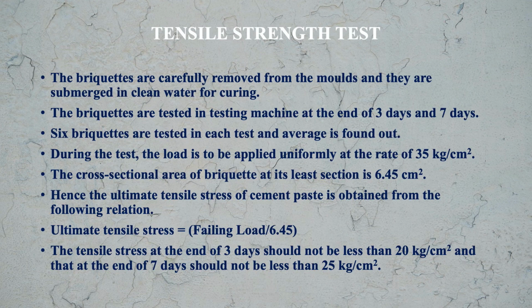Now the briquettes are carefully removed from the molds and they are submerged in clean water for curing. The briquettes are tested in the testing machine at the end of 3 days and 7 days. 6 briquettes are tested in each test and the average is found out. During the test, the load is to be applied uniformly at the rate of 35 kg per centimeter square.